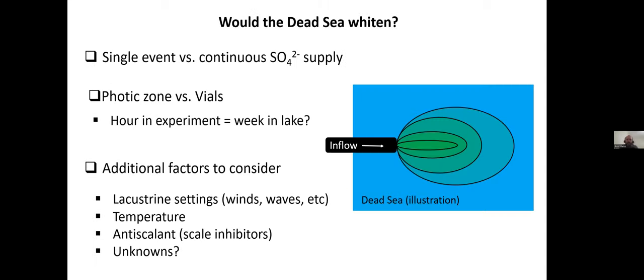So all of the experiments we've seen so far suggest that a whitening event is not likely to happen. However, we should consider that laboratory experiments are not the natural system. In the experiments, I have a single event of mixing. Basically, I immediately mix the two end members. Whereas if I discharge the brine into the lake or seawater, close to where the brine comes in, I'll have the composition of what's flowing in. Far away, the lake won't even know that something entered. And in between, I'll have this gradient of concentration, and only one place in space and time would have the concentration or the chemical composition of the experiment.